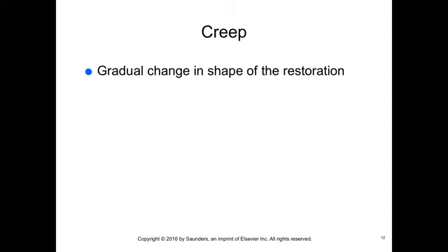Creep in dental amalgams refers to the gradual change in shape of the restoration from compression by the opposing dentition. This phenomenon is associated with the gamma 2 phase seen with lower copper alloys and results in deterioration in margins. High copper alloys exhibit far less creep.